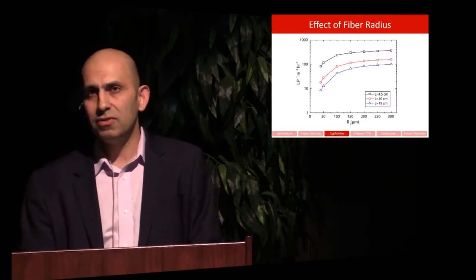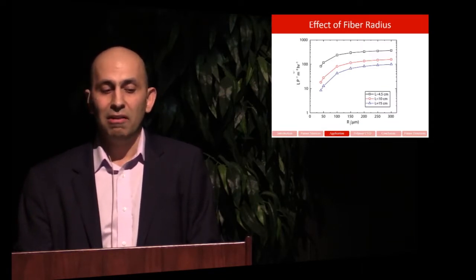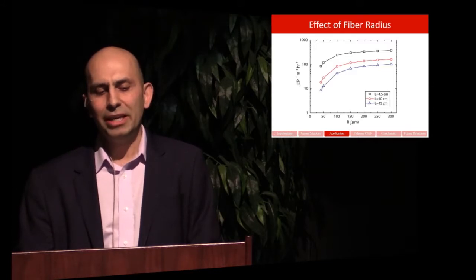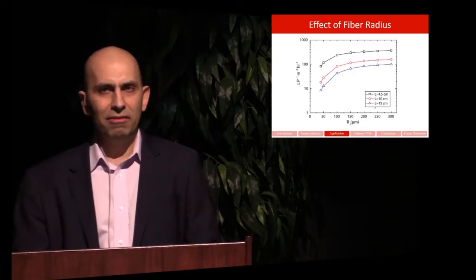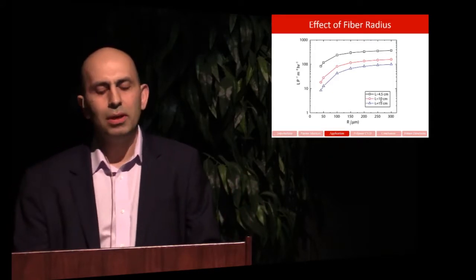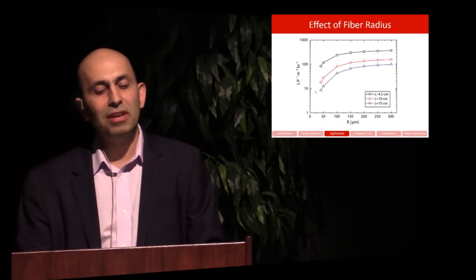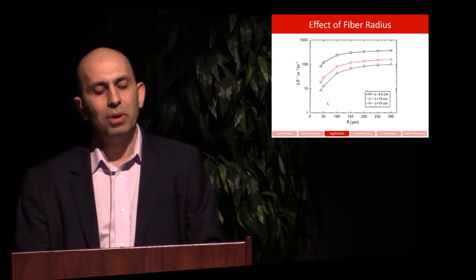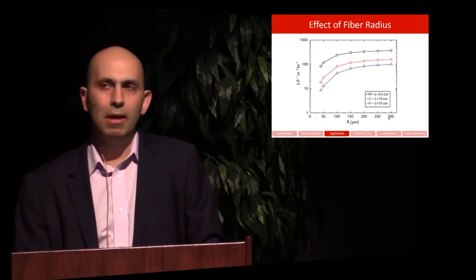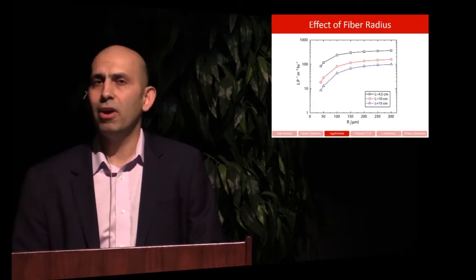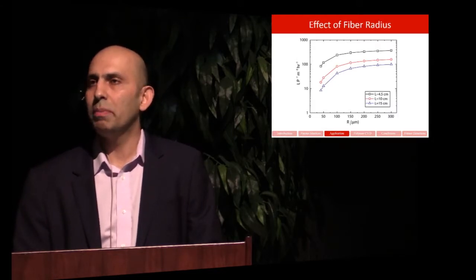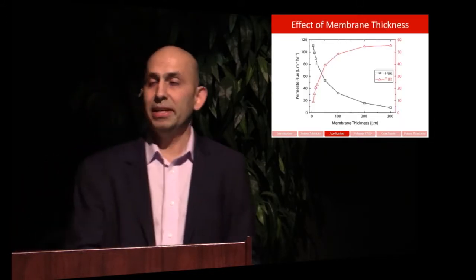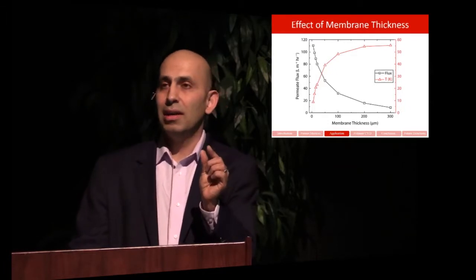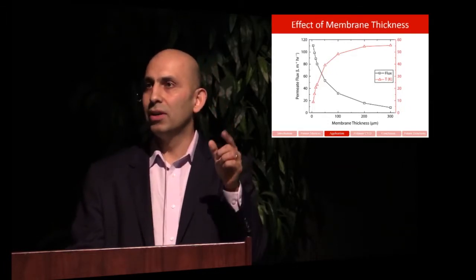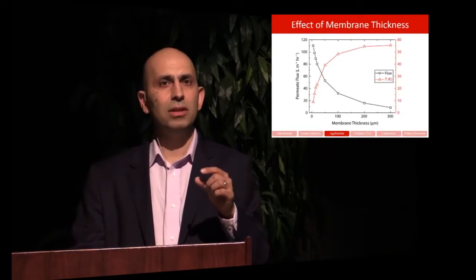Here you see the radius of this fiber, and here you see some sort of indicator of flux. These are the lengths of the fibers, how long they need to be. And again, as you see, we can achieve significantly high flux for membrane beyond certain range in diameters. Basically, what we're trying to do is identify the parameters of the membrane we need to make in order to produce water at lower cost. And here's the thickness of the membrane. The smaller the thickness, the less pathway for water to transfer. So if the water transfers faster, you get higher flux.